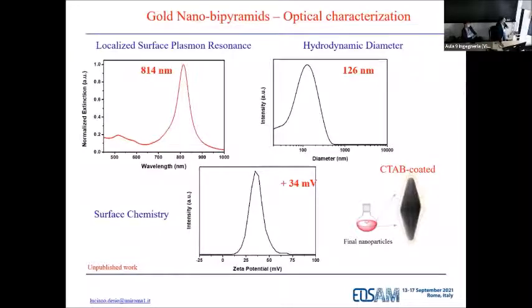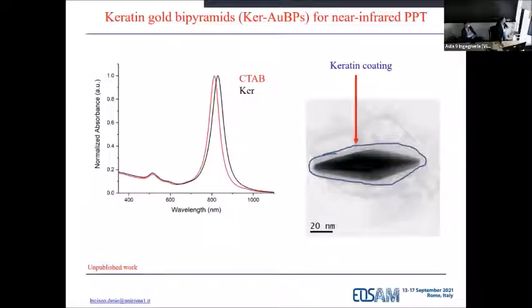We tried, and you can see here very well that we succeeded in coating those particles with keratin again, and you can see also the shift of the plasmon band, thus highlighting the strong sensitivity of those particles.